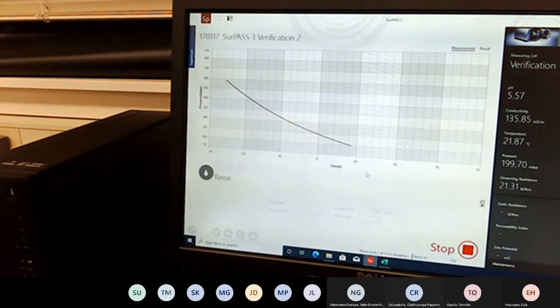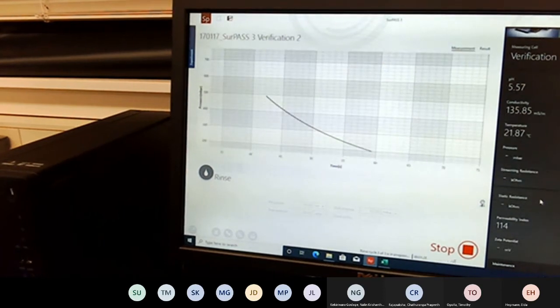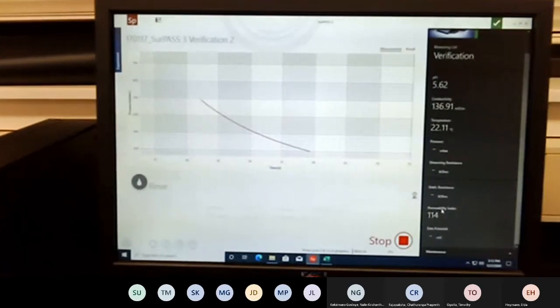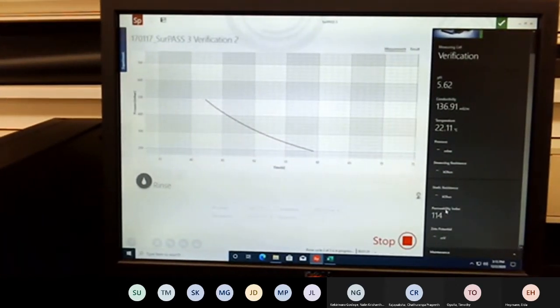And when you're rinsing your sample, generally the first run is going to look a little different from the second, third or fourth runs, mainly because this is the first time that the sample is interacting with the liquid. Over here on the right hand side, you may notice something called the permeability index. Each of the sample cells is going to have its own parameter that will determine if you have too much flow or if the gap's too big between either the two pieces, or in this case, the cloth itself. For the verification cell, permeability between 100 and 130 is ideal. So we're smack dab in the middle right here.